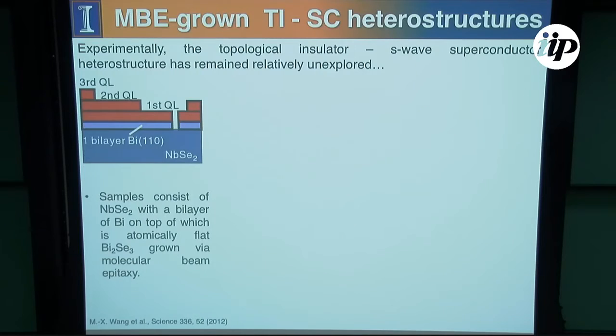Basically they start off with niobium selenide, which is a superconductor. It's actually a more interesting superconductor than we originally had thought. In the later parts of the work, we actually started taking into account the real band structure of this superconductor to try and give a more realistic picture of the kind of pairing that was going on and exactly where we could find interesting states.